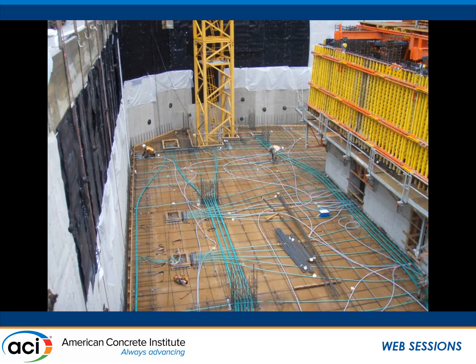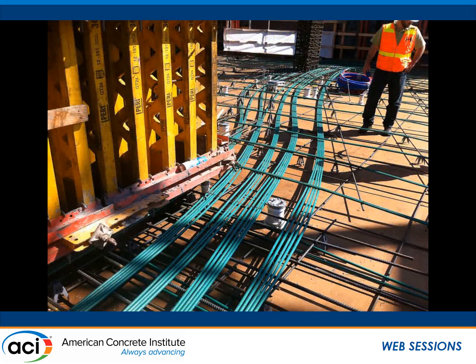Basically, that's stress leave-outs. On closure pours, since the concrete for the closure pour is locked in by the slabs on both sides, we use a more stringent shrinkage requirement down to 0.025, and a lot of times what they do is they use the same slab mix, and they add a gallon of shrinkage reducer admixture per yard. Here's some shots of the tower, looking at the slabs and the construction of the PT.